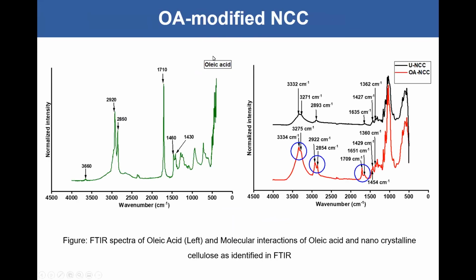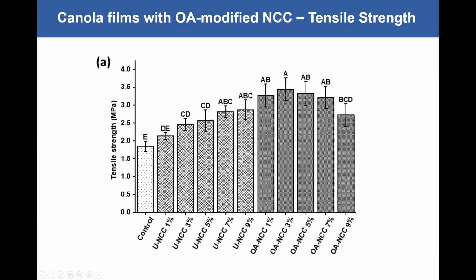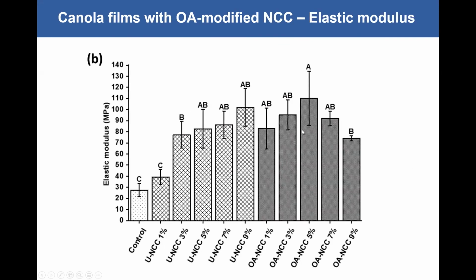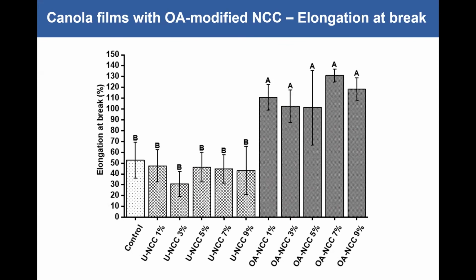With that, we did the FTIR to recognize the chemical and molecular interaction of oleic acid with nanocrystalline cellulose, which we confirmed with the FTIR. And then we looked at the mechanical properties. So as you can see in here, even with the oleic acid based modification, we managed to improve the tensile strength. At the same time, we managed to improve the elastic modulus as well as the elongation at break.